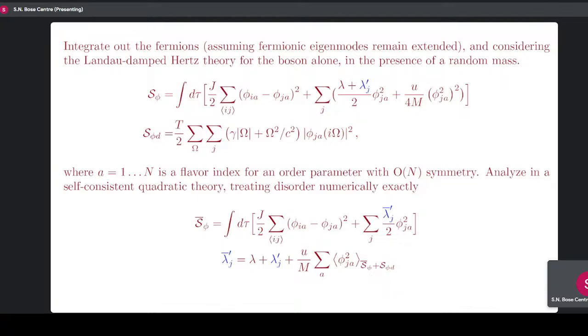This top line is exactly the theory you write down for a random-mass Ising model. It's just a random mass term, and phi is your Ising order parameter. But because you have fermions, there is a small omega term in frequency that's the Landau damping. I should say at this point, it is important that phi be multi-component. Or I misspoke a little bit. This is really the O(N) model, right? N is the flavor symmetry of phi. The N equals 1 case is a little different. But fortunately for the cuprate, the relevant order parameter is N equals 2, we think. Anyway, this is the theory we want to solve.